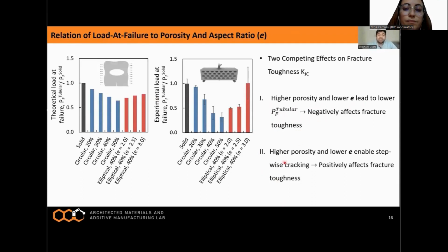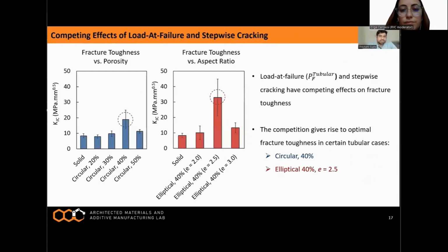However, the same characteristic of higher porosity and lower aspect ratio in the tubular architected material facilitates the stepwise cracking, which in turn increases the material's fracture tolerance. Hence, we can say that load at failure and stepwise cracking have competing effects on the failure tolerance.